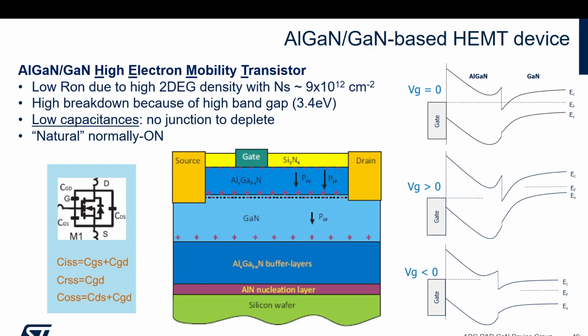The important thing is that this combines the benefit of high band gap, so like in the case of silicon carbide, you can go to reasonably high voltage within the layer. And of course, in this case, you combine also with the fact that you have very much reduced capacitance. You have no junction to deplete, while in the case of the conventional MOSFET, you have a lot of junctions that give you parasitic effects.